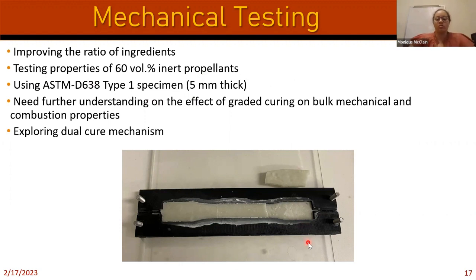So we have 2 cure layers, but point being that, obviously that cure layer is going to be pretty weak. So this is an example of how it got stuck and my students are trying to take it out. And then of course it started breaking at that interface where it was curing. So it's going to be really important to understand, are there ways to improve that adhesion between those 2 cured layers? Or do we have to explore something like dual cure mechanisms where we partially UV cure and then complete the cure thermally later? So these are things that my students are working on now. So they're looking at testing cast samples. They're looking at testing 3D printed samples as well.